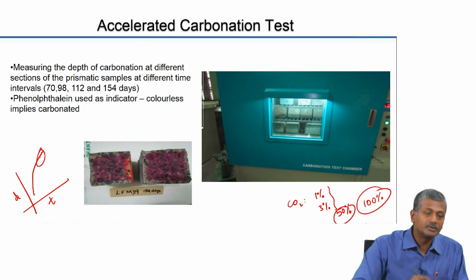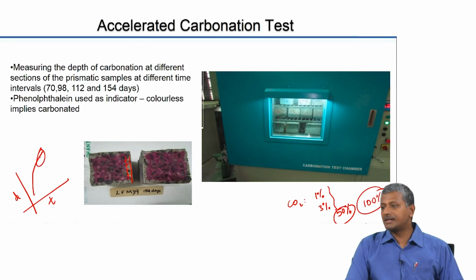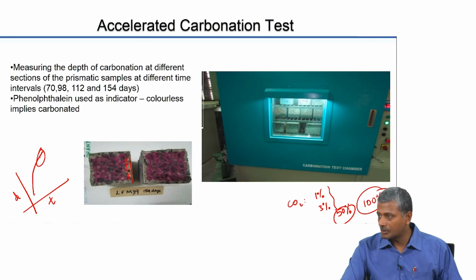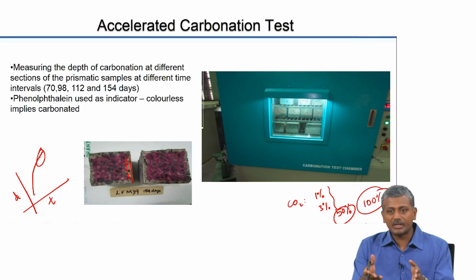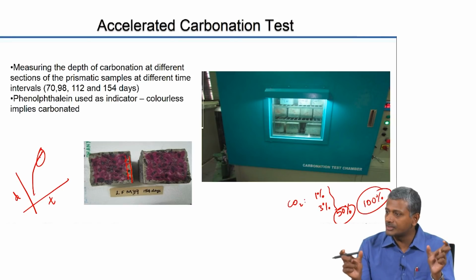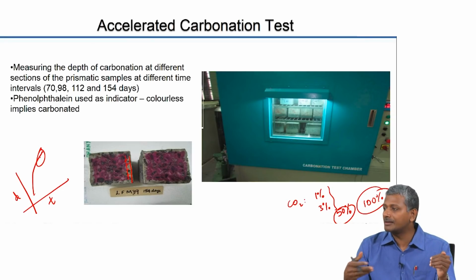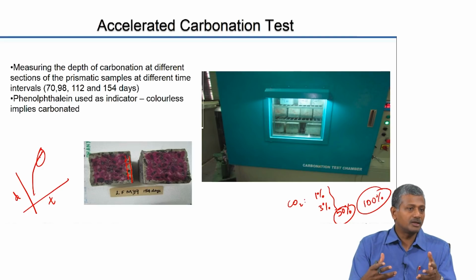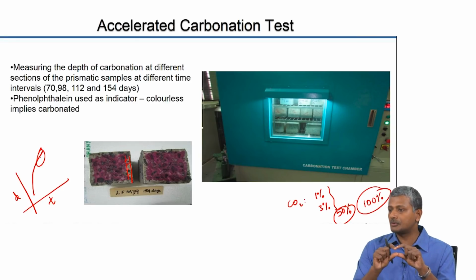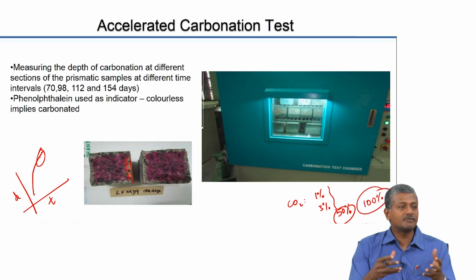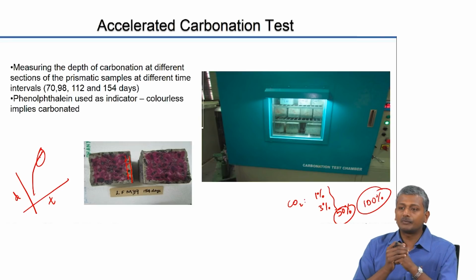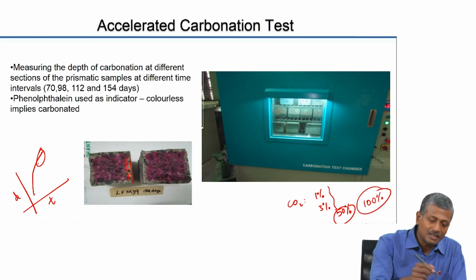Why does it taper off? Why does the rate of penetration of CO2 drop with respect to time? Probably not saturation. What is actually happening is your surface zones are getting converted to calcium carbonate. There is densification happening. So, the penetration of CO2 is going to get reduced with respect to time. So, with normal ordinary Portland cement concrete, you will see that the densification caused by the surface conversion of lime to CaCO3, calcium carbonate, tends to densify the concrete, and that slows down the rate at which your CO2 further propagates. So, you start seeing a limiting sort of a relationship.